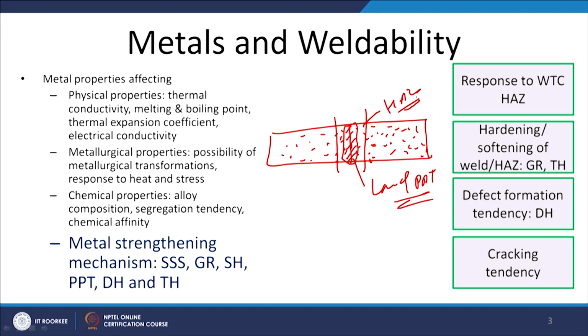So in both the cases, whether it is the fusion welding or the plastic deformation based approach, the loss of the precipitates is going to take place from the weld zone, and the partial loss of the precipitates will be occurring as per the amount of heat which is being supplied for the development of the joint, and it is being transferred to the heat affected zone. So, as per the extent of the loss of the precipitates from the heat affected zone, that will be determining the extent of softening or the reduction in properties which will be taking place.